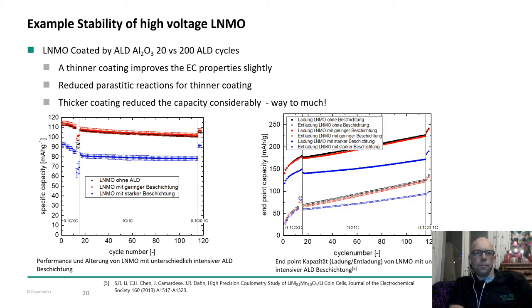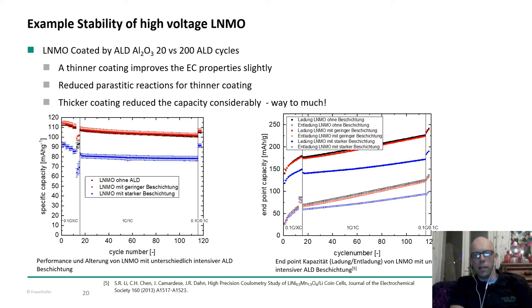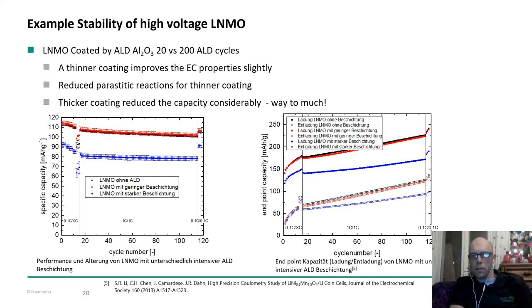It's more in the details — more like engineering rather than a huge improvement. But looking at the slopes and endpoints of the curves, you can clearly see that a thick coating drops capacity significantly. If you stay in the thin range — and we think we need to go even thinner — we believe we can extend cyclability without a big capacity penalty.